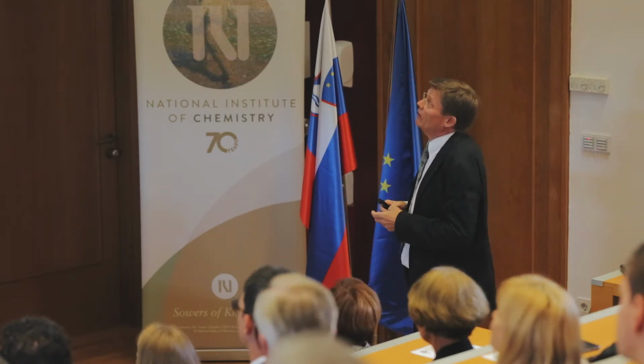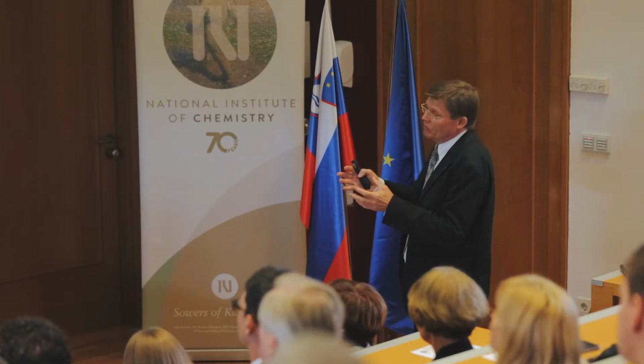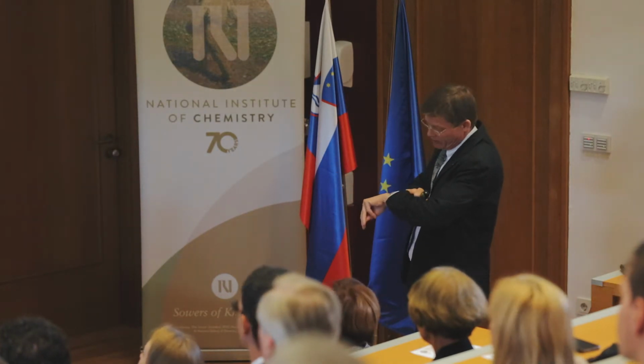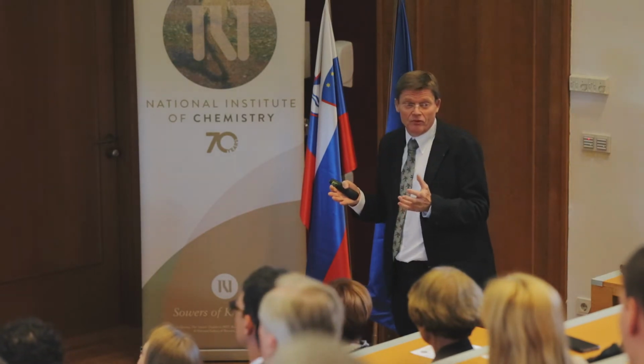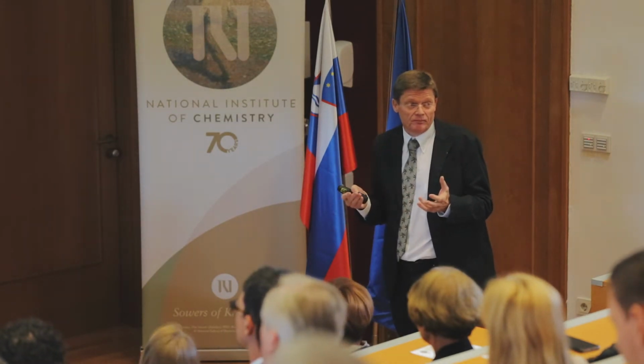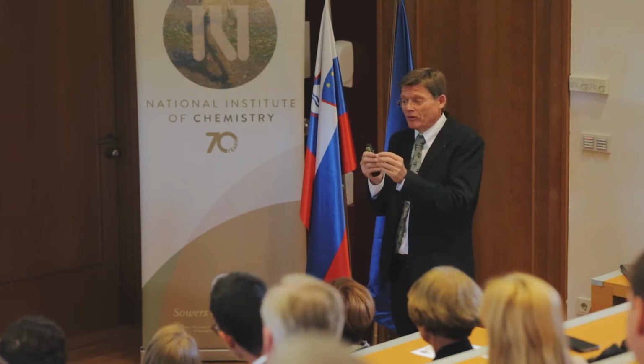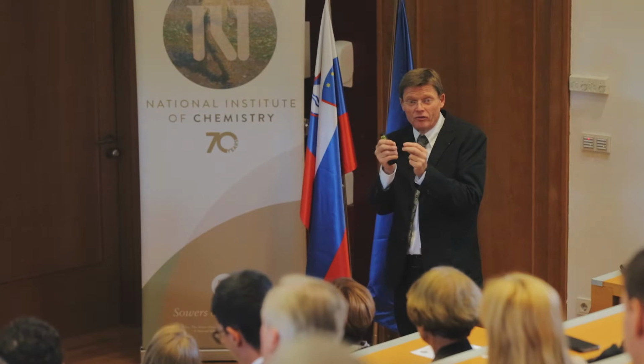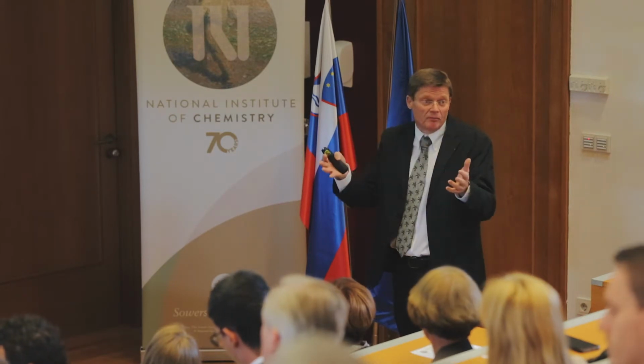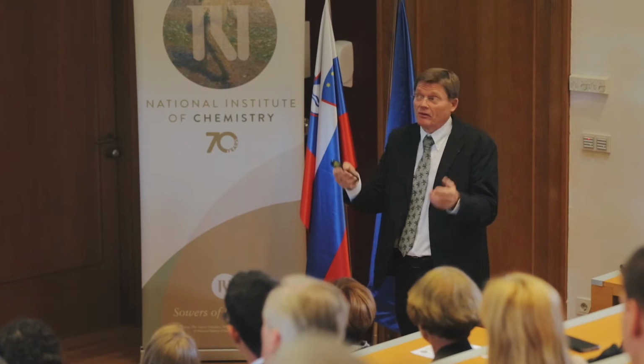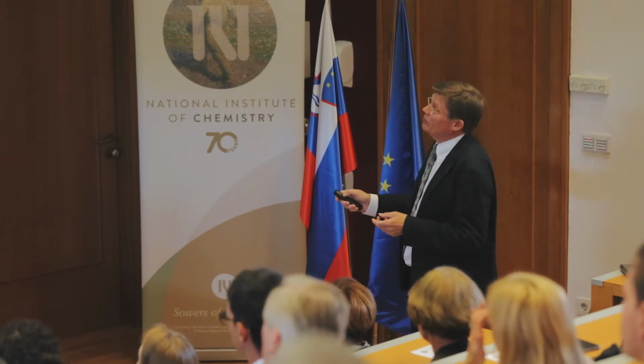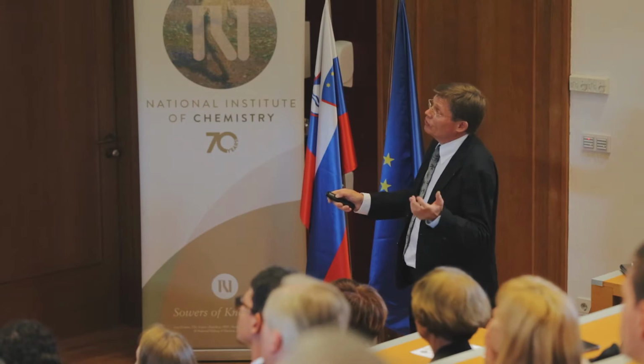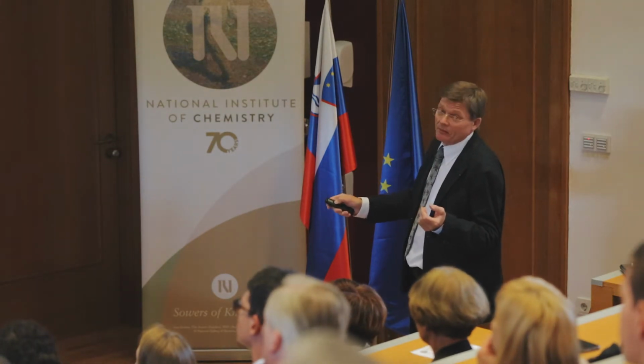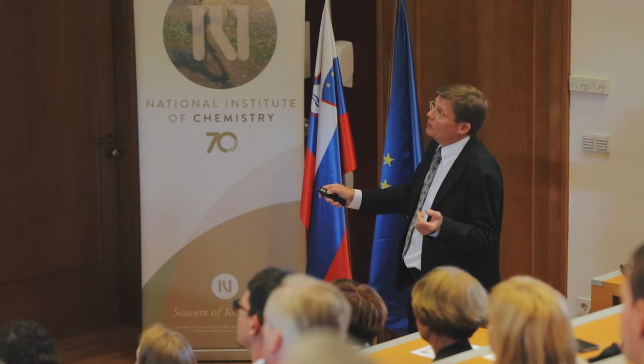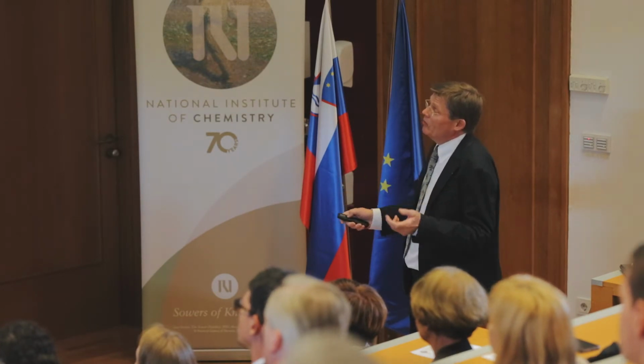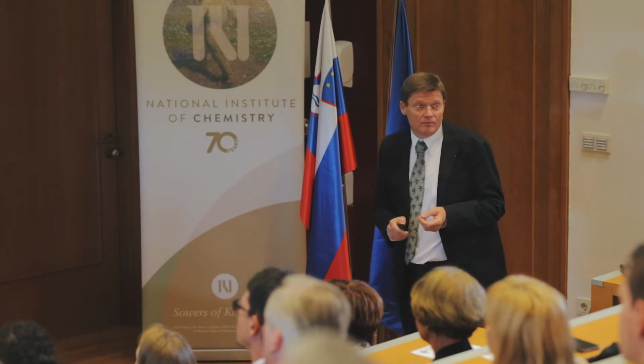The second part, let's look into some systems where the energy storage is very large. This is typically what you have in a battery. Then you're not content with having a very, very small variation, very small uptake of something. You want a big uptake of lithium, for example, and the electron. So this is a battery, this is your electrolyte. Now, in contrast to a fuel cell, you store your material here and there. So this uptake must be very large. And this again can be mimicked by this kind of circuit.